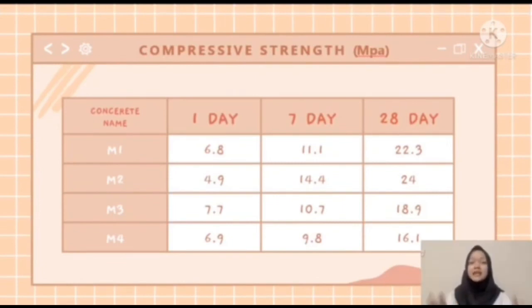Basically, this is the table for compressive strength, which is the first test to determine strength properties of concrete. A compression testing machine with a capacity of 2000 kN was used to assess compressive strength. The test was carried out on 150 mm cube specimens at ages of 1 day, 7 days and 28 days.